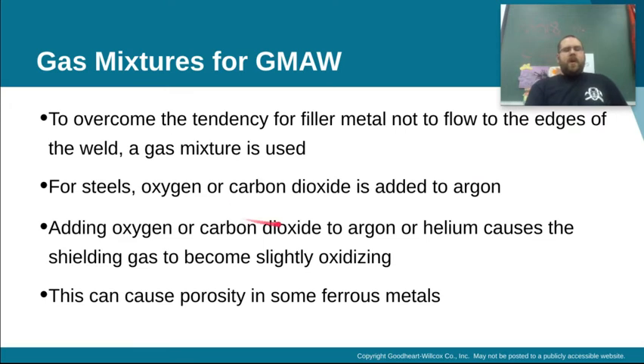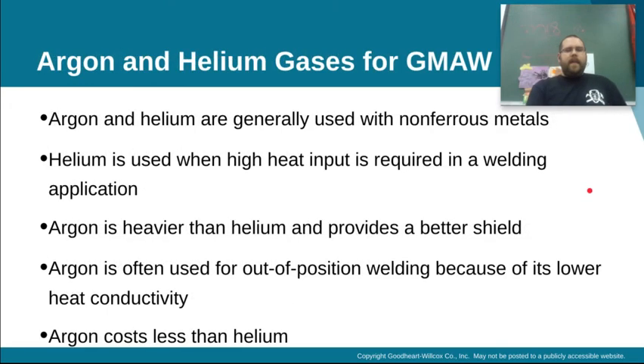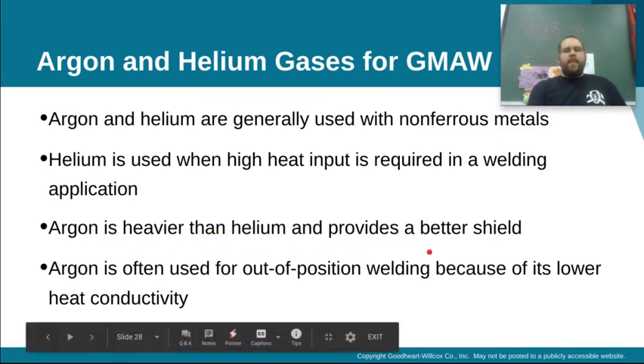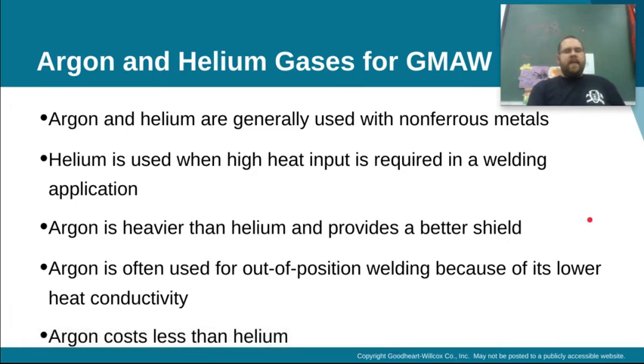Adding oxygen or carbon dioxide to argon or helium causes the shielding gas to become slightly oxidizing. This can cause porosity in some ferrous metals. Argon and helium are generally used with non-ferrous metals. Helium is used when high heat input is required in a welding application. Argon is heavier than helium and provides a better shield. Argon is often used for out-of-position welding because of its lower heat conductivity, and argon costs less than helium. Helium is super expensive.